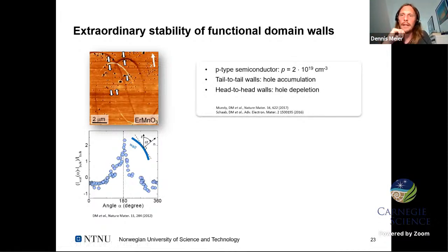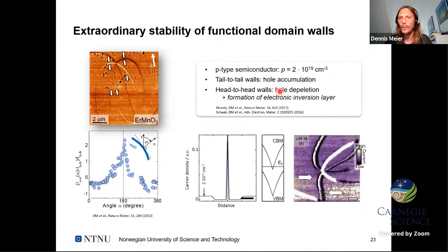What's happening here is that we have a p-type semiconductor. Whenever we have tail-to-tail walls, which have negative bound charges, the holes like to go there for screening, and the conductivity increases. At the head-to-head walls, it's the opposite effect. The holes deplete, and we have reduced conductivity. But it can even go one step further.